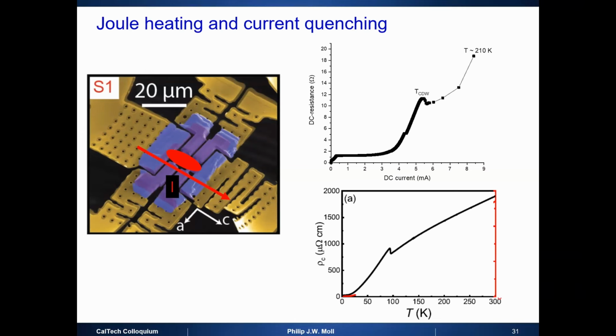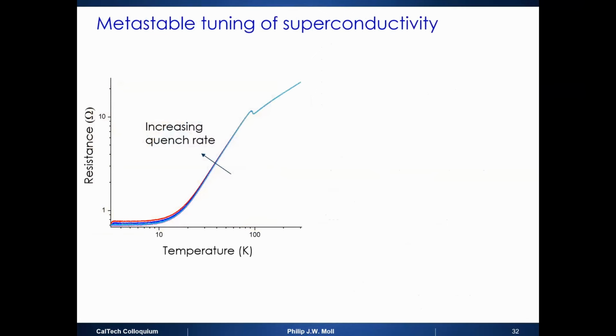And now you switch it off. The system crashes down. Thermal time constants are tiny because it's cubic microns, right? So this tiny, tiny time constant, so you can really achieve massive cooling rates. And indeed, what you can see is that the out-of-plane resistance, as a function of quench rate, goes up. This is the disorder you put in, okay? I've shown you here up to this. We're now pushing this forward and forward. I actually don't know whether the number is in the cryostat right now, but it's pushing it upwards. And so this actually works, right?